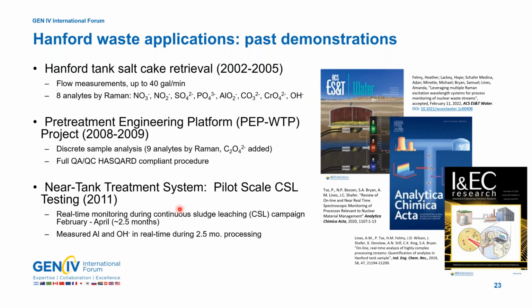In the early 2010s, we also supported a pilot scale continuous sludge leaching program where we used a Raman probe that could measure the boehmite and gibbsite dissolved in the continuous sludge leaching project, where we can measure aluminum being dissolved as aluminate and hydroxide in real time. And this was a 24/7 application where we ran continuously for over 2.5 months, giving immediate feedback to the operators as they were doing the sludge leaching. Some of the applications and the techniques that we use are summarized in some of the publications I show here on the right-hand side.